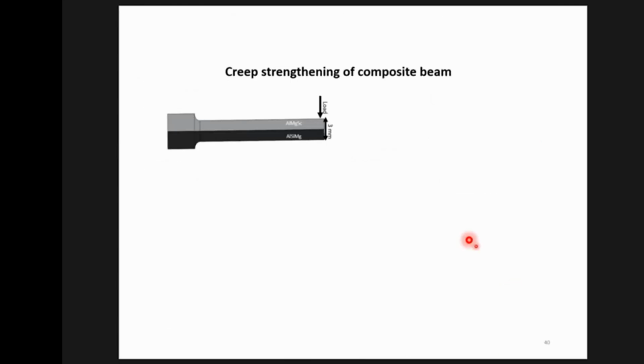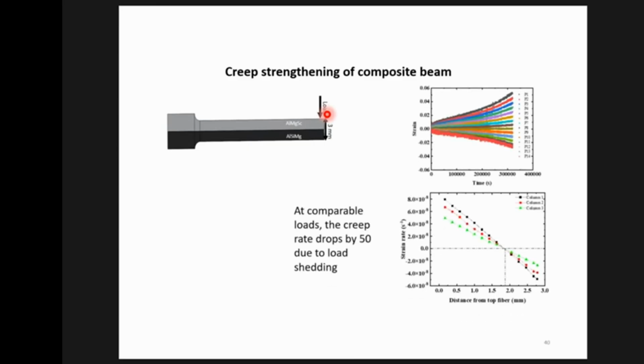So this is the sandwich that was made. One of them is on top and the other is on the bottom. And then you load it like a cantilever. And if you look at the strain rates, you will of course see that the strain is not symmetric, because now you have two different materials. One side is stronger than the other, and so the neutral axis shifts. But it's the magnitude of the strain rate that you achieve which is interesting here. For the same bending moment, you would have either a very soft material or an extremely hard material. By making the sandwich, the soft material's response has actually decreased by about 50 times, simply because the load has been transferred to the harder material.